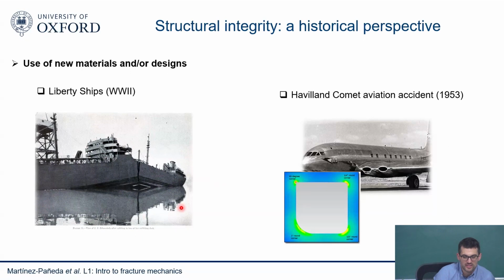Another classic example is the Havilland Comet aviation accident. You may wonder, when you fly on a plane, why the windows are rounded. Well, of course, you know that sharp corners lead to stress concentrators, so that's why we make our windows rounded. Back in the day, in fact, the windows had sharp corners, like the ones in our house, basically. And you can see that nowadays it's quite blunt, quite smooth. And you can see why.